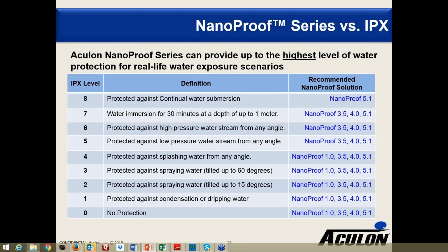So we ran a series of tests to basically look at what we can provide. And on the right-hand side here, you can see through IPX level 4, which is basically splashing water from any angle, NanoProof 1.0 does a very good job. And NanoProof 1.0 is certainly the least expensive of these treatments.